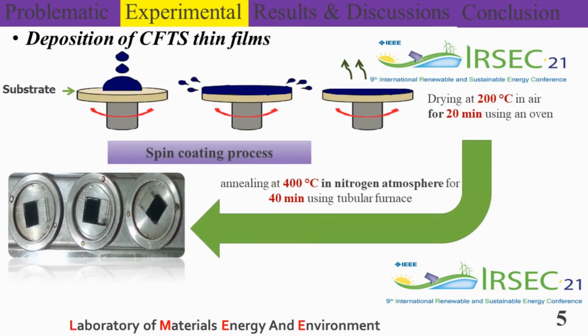a spin coater was used to deposit the CFTS thin films on cleaned soda lime glass and on fluorine tin oxide glass substrate. Then the obtained thin film was dried in air at 200 degrees C for 20 minutes to remove the residual organic materials. After that, the synthesized thin film was annealed at 400 degrees C for 40 minutes in nitrogen atmosphere using a tubular furnace.